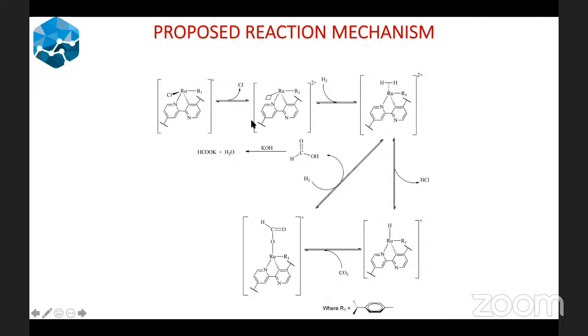So this reaction is taking place under basic conditions of KOH. So that's what we proposed. There are other mechanisms in literature, but we thought this is a plausible mechanism for formation of your formate from carbon dioxide in the presence of KOH as a base. Remember, if you have an organic base, you form formic acid. But of course, if you have an inorganic base, you form the formate ion.